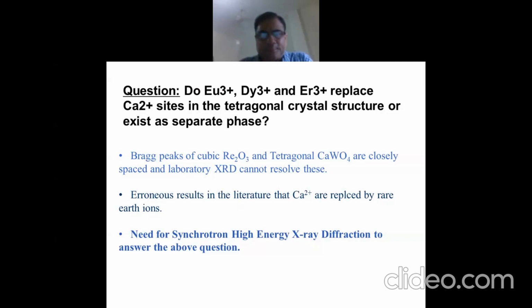In fact, the Bragg peak positions of cubic rare earth oxides and tetragonal calcium tungstate are very close to each other, and if you use a laboratory X-ray diffraction system, you cannot resolve these peaks. Moreover, in your laboratory XRD system, you have copper K alpha 1 and copper K alpha 2 X-ray lines, and the peaks are broadened. The peaks of rare earth oxides and the tetragonal phase of calcium tungstate or calcium molybdate mix, and you see very broad peaks. It is not possible to resolve them and answer whether the calcium ions are replaced or whether there is a phase coexistence.